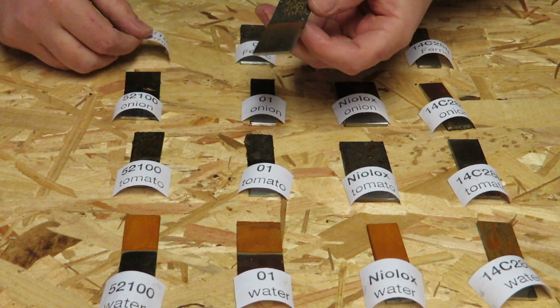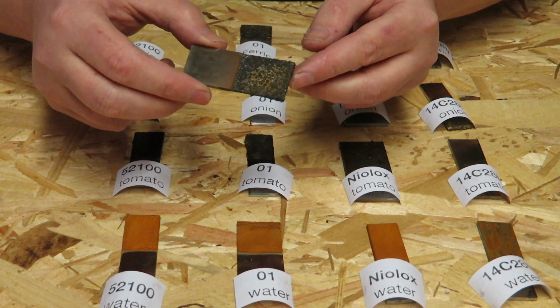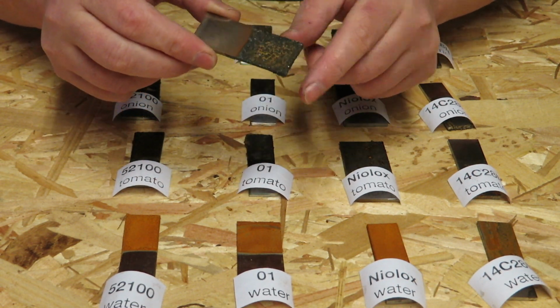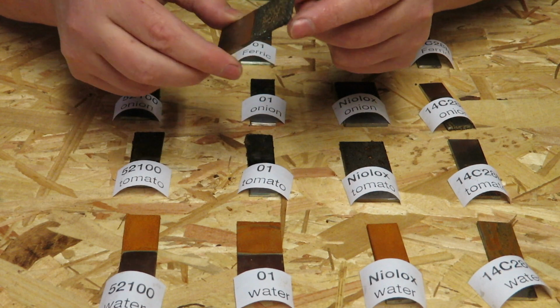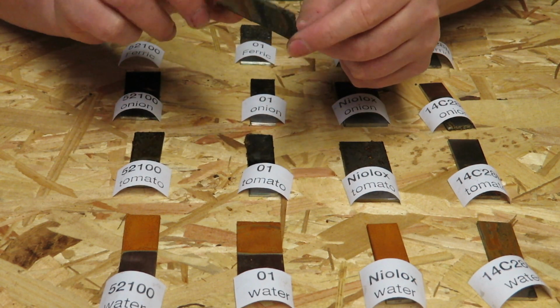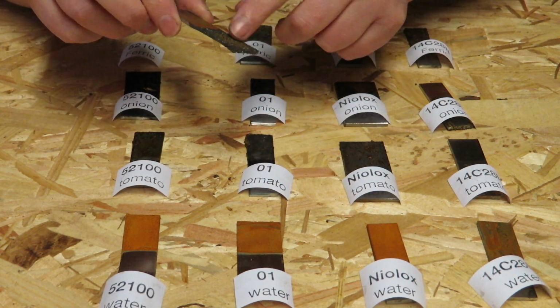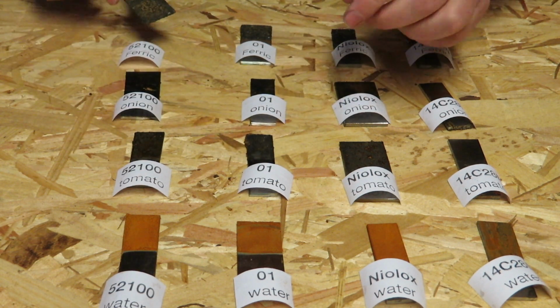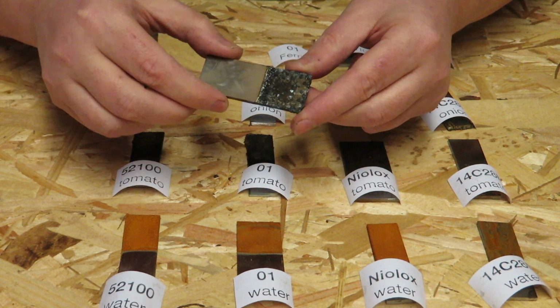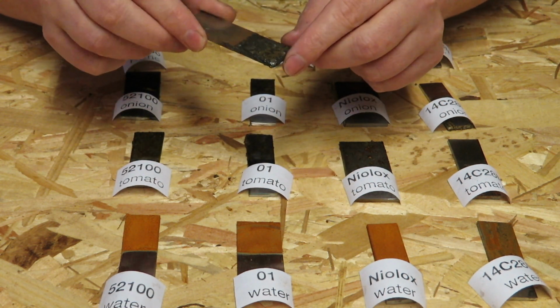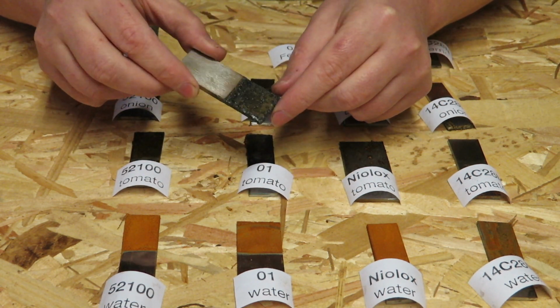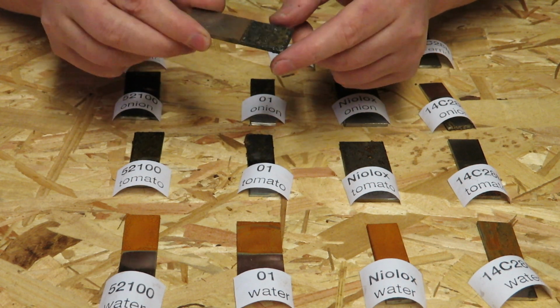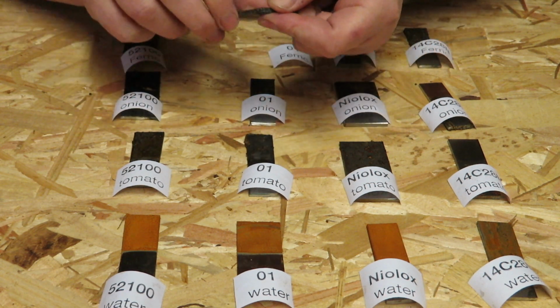So the 52-100, that one, it's almost crystallized on the steel there. We've almost got crystals forming. It's definitely deformed and changed shape slightly, so that's really bitten into this steel. The 01, very similar. We seem to have much bigger crystals on there that formed. Again, it's changed almost the structure of the steel.